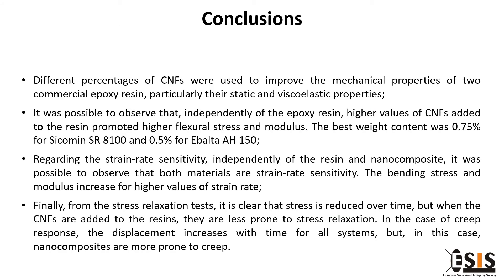Different percentages of carbon nanofibers were used to improve the mechanical properties of the commercial epoxy resins. In summary, independently of the epoxy resin, higher values of carbon nanofibers added to the resins produce higher flexural stress and modulus. Regarding the strain rate sensitivity, it was possible to observe that both materials are strain rate sensitive. From the stress relaxation test, it is clear that stress is reduced over time, but when carbon nanofibers are added to the resin, the material is less prone to stress relaxation.